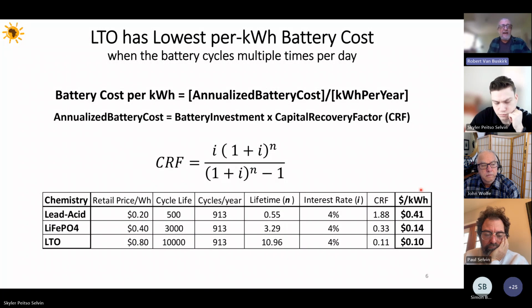But we see that when you're cycling the batteries 2.5 times per day, the lead acid battery is only going to last about 6 months, a little over 6 months. The lithium iron phosphate battery, if you're cycling 2.5 times per day, is going to last about 3 years, whereas the lithium titanate, the LTO battery chemistry, should last 10 years. And because of the long lifetime of the LTO, you're amortizing the cost over many more kilowatt hours, and the per kilowatt hour cost of the electricity being managed by that LTO battery is now down to only 10 cents per kilowatt hour. So that's the goal, right?